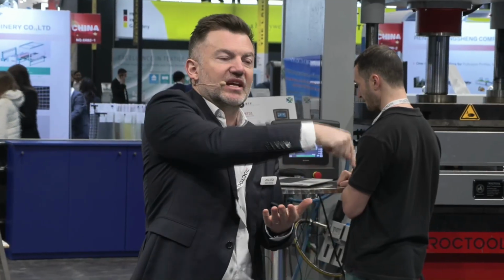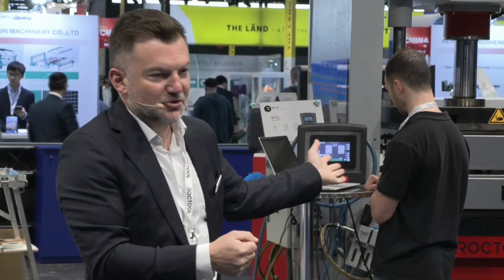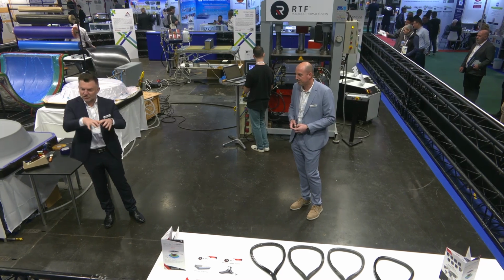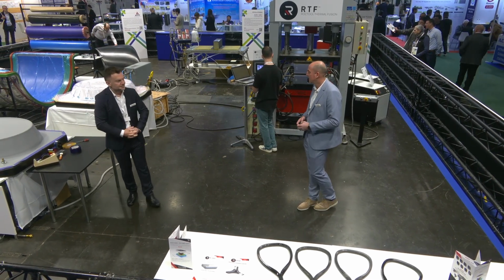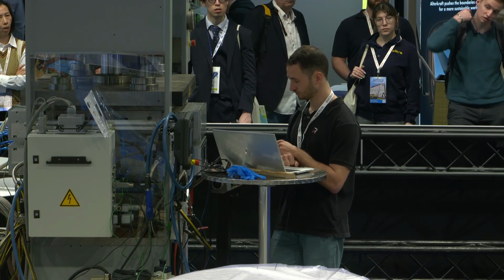And finally, I could have another piece that maybe was molded before in a section of the part that also would be bonded and welded because it's the same matrix. So in one shot, in these 12 minutes, because we're using a heat platen and an aluminum insert, we make a structural component in one shot. But you can see, we start the heating with our induction generators. I will describe the power and the range of our equipment in the next slide. But we are able to reach, in this case, for this live demonstration, 100 degrees per minute. So in less than 3 minutes, we'll be able to reach the transformation temperature of 260.